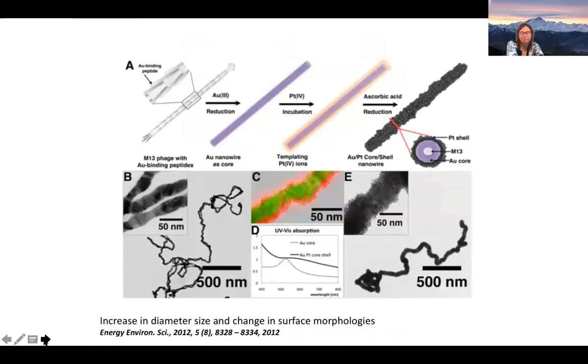This particular example that I'm showing here is a nanowire. We have a virus that can grow these gold nanowires, grows these nice gold nanowires seen in the figure B and C. Figure C is actually an elemental map using high resolution transmission electron microscopy. We can map out the elements on this, and this one is showing the green is gold, and the red is platinum. So we had a virus that could first grow gold and then grow platinum on top of that in a really controlled way.